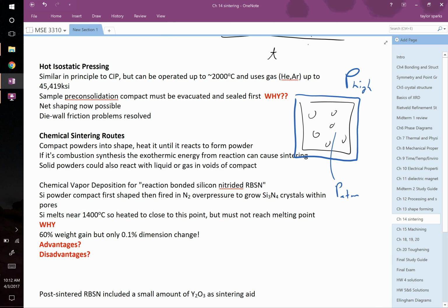If this was permeable, then your helium gas would go inside of here, and you've got the same pressure on both sides. It's not going to actually make it smaller, right? So it's got to be gas impermeable. That's the hardest part of this process. This is the best process out there for getting the densest, strongest, all the way dense samples, but it's going to be a slow process, right? It's not going to be fast like SPS where you can achieve nanostructures, and you have to put this gas impermeable layer on it, which is kind of tricky because then you have to get rid of it probably when you're done. But this is definitely the best way to get the densest samples possible.